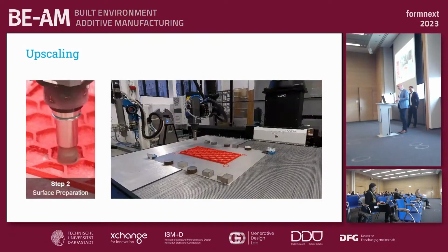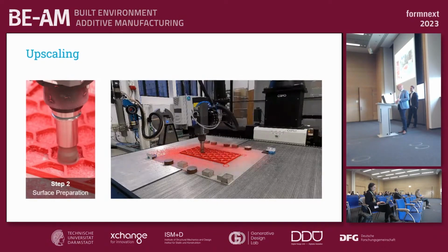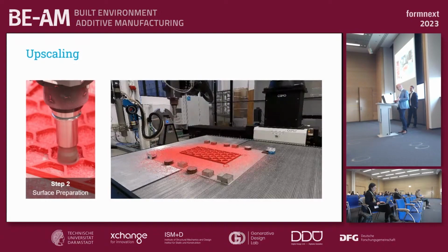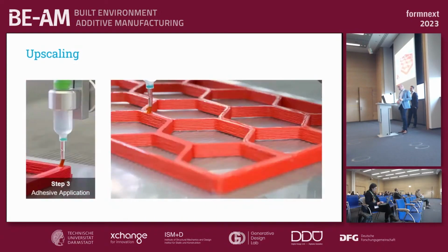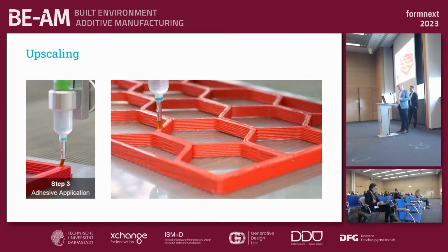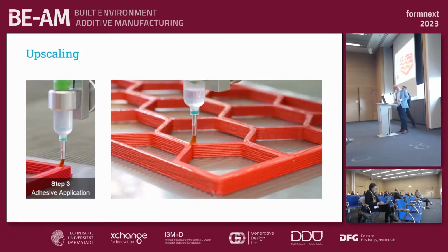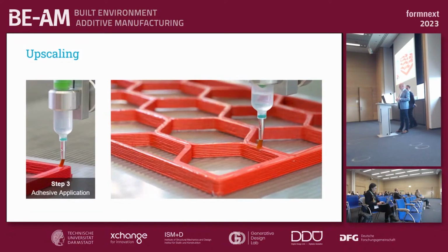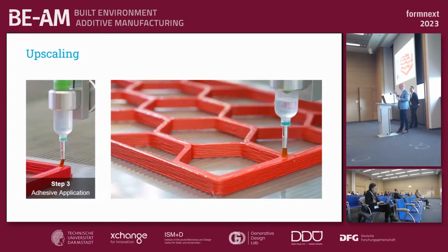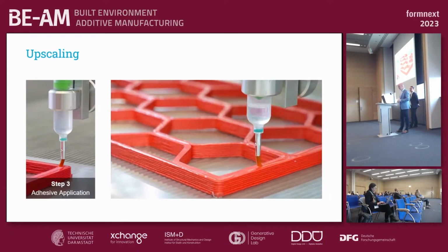And then in the next step, we grind the top surface. So the top surface is milled off, also robotically, just to get a perfectly smooth surface again to be able to glue on it. And that gluing is then done in the next step by this also robotically operated reservoir, applying the glue with specific pressure and specific speed. And this glue is UV curing, so it only gets rigid if you apply UV light from the sun or from an artificial light.